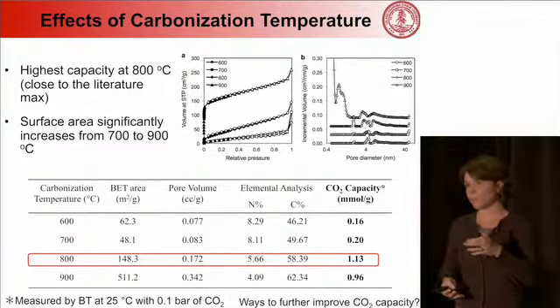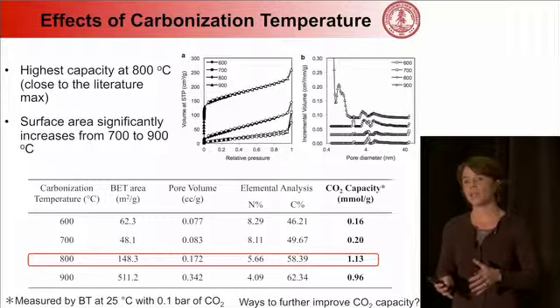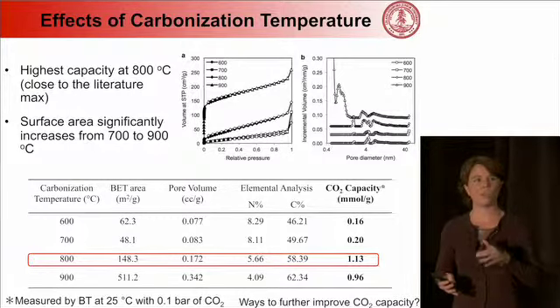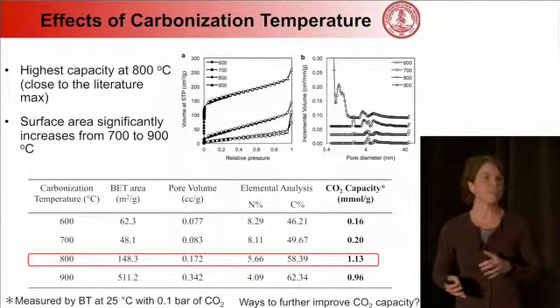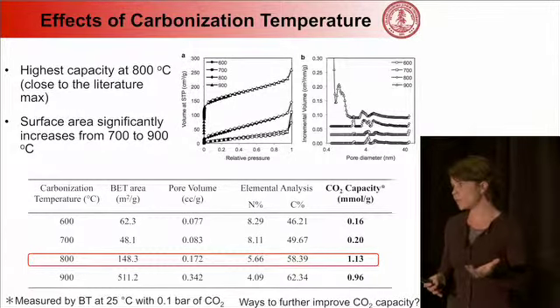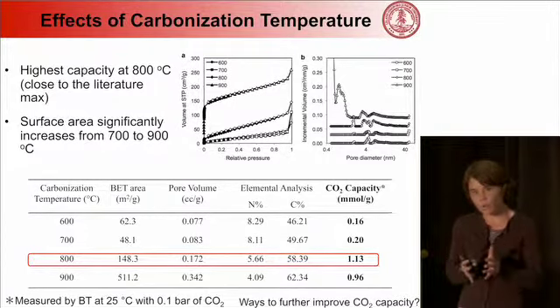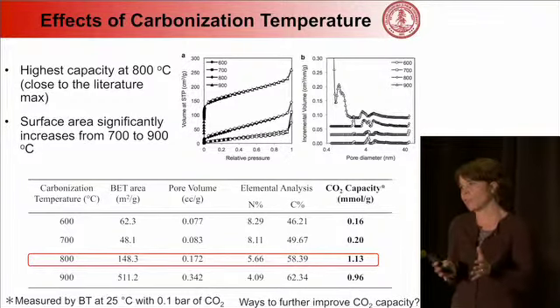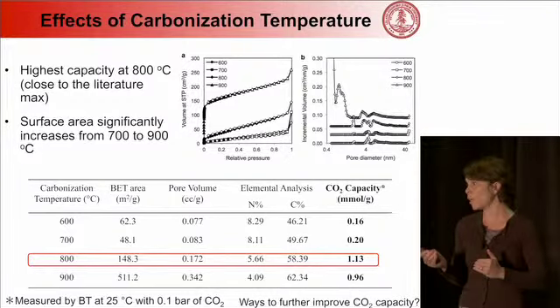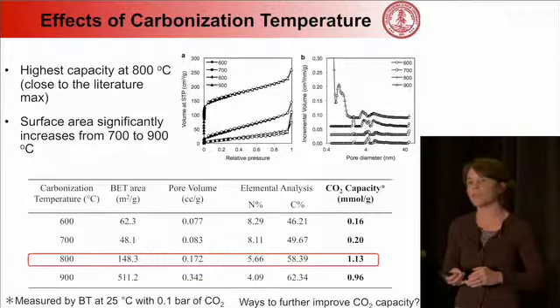But there's another kinetic term built into the kinetics, and that's how fast the CO2 can get in and out of the pore space. And so it's the diffusion kinetics. And so if the pores are too small, it may be difficult for the CO2 to get in, it may be difficult for the CO2 to get out. So that's one aspect of the tunability of the pore size.